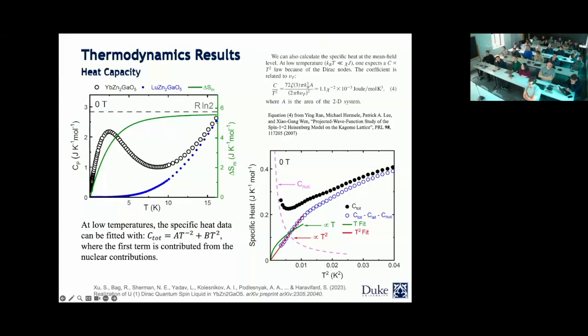And I would like to draw your attention to this paper. This paper in 2007, which Patrick Lee and colleagues published, is a theoretical interpretation of a Dirac quantum spin liquid candidate for Kagome materials. What we did is start to look at this, and this formula says that at zero magnetic field, C over T squared is going to be linear. So at very low temperatures, the specific heat needs to go as T squared, which is what we are seeing in zero field as well. That was an indication that most likely we are dealing with a Dirac quantum spin liquid rather than a spinon Fermi surface.